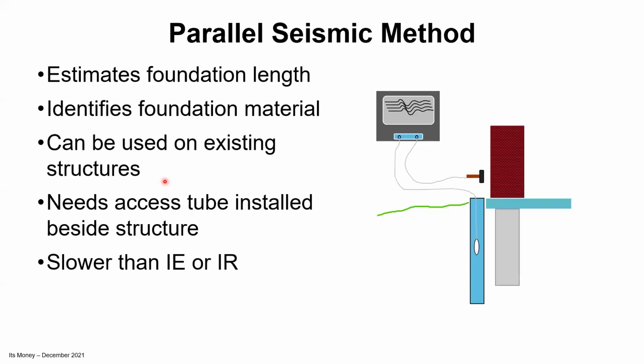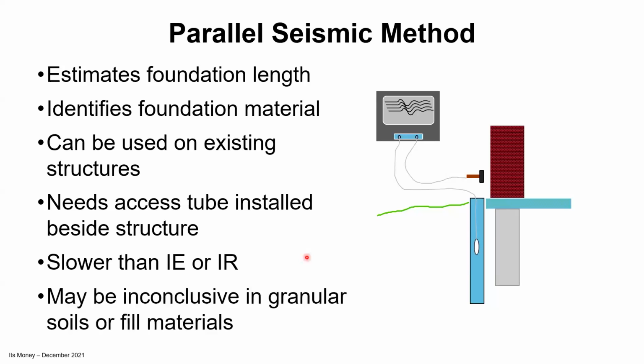Because of that, it's also slower than the impulse echo or impulse response because the transducer is lowered in uniform increments down the shaft as we generate a hammer blow at each increment. So it takes quite a bit longer to perform. The kicker here is that it's a test that may be inconclusive in granular soils or fill materials because we're relying on the propagation of the sound wave from the foundation to the access tube. The granular materials do not conduct sound as well as a cohesive material, so the test may be inconclusive in those conditions.